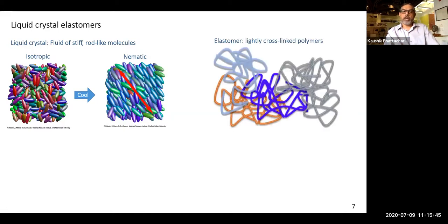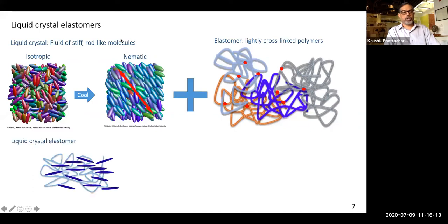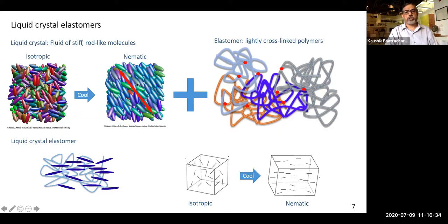These are rubbery solids. And these are made out of a large number of polymer chains, long floppy molecules. These are typically liquids. But when you cross-link them, so think about old spaghetti. So now it acts as a solid, but it's a very soft solid because all of its elasticity comes from the entropy rather than the internal energy. So liquid crystal elastomer is a combination of these two, where you create polymer chains with this nematic mesogens. So notice that this is, though I draw it like this, these are really a molecular picture. This is only 2 nanometers. Each mesogen is about 2 nanometers. So there's enough free volume that these mesogens can still undergo their isotropic to nematic phase transitions. But as they do, they take the polymer chains along with it, so the solid actually changes shape in a dramatic way.